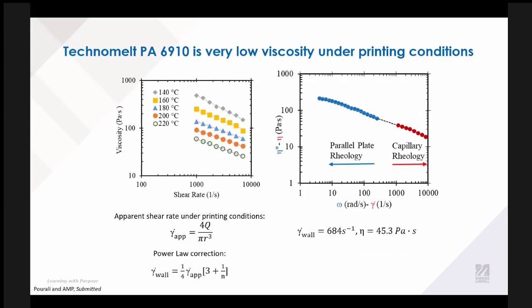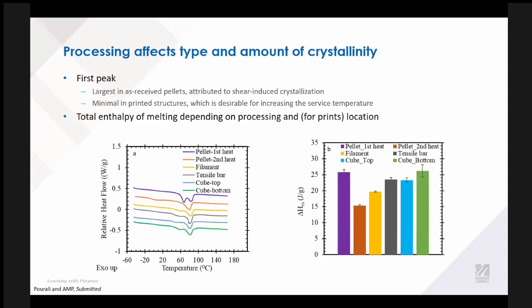So getting to this idea that we have these void-free structures, we think that some of this is because the material has a very low viscosity under print conditions. So we're seeing at a shear rate that is consistent with typical printing conditions, we predict a viscosity of this material of around 45 Pascal seconds, whereas typically for printed structures, the viscosity would be more in the range of 150 or so Pascal seconds. And so we're substantially lower than that. And we think that is helping with this ability to flow while still balancing needing to set up rapidly so you don't get slumping.